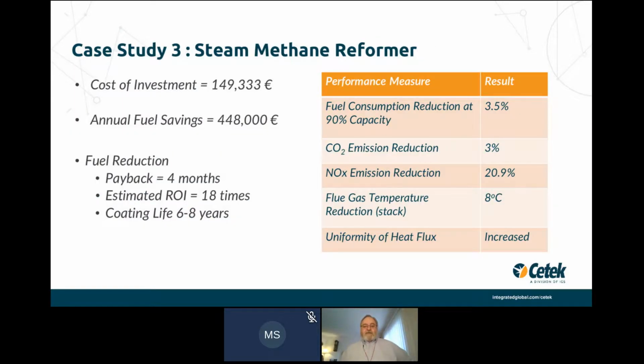These are the results. On the right-hand side, the chart shows that fuel consumption at 90% capacity was reduced by 3.5%. CO2 emission reduction was around 3%. NOx emission reduction, I measured at 20.9%. And flue gas temperature in the stack came down by 8°C. They noticed a much more uniform heat flux.